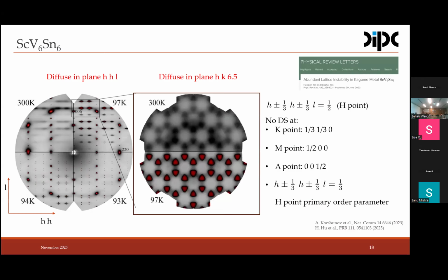So essentially, we don't see diffuse scattering at the K point or A point or M points, which are the other high symmetry points in the reciprocal space. But we see a diffuse signal, a precursor of the charge order, at L 1/2. I have to recall that the charge order happens at L 1/3. So 1/3 and 1/2 are two different propagation, two different wave vectors in the reciprocal space. So the L 1/2 is actually the primary order parameter that drives the phase transition of